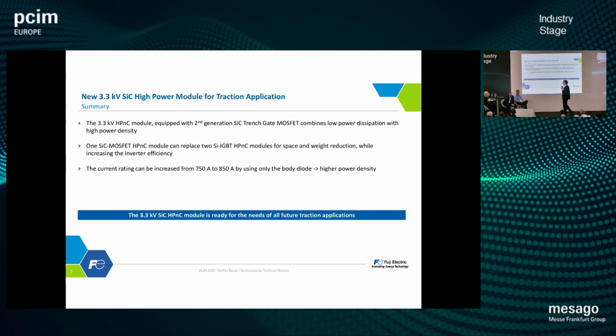So to summarize this, the 3.3 kV module is equipped with our second generation trench MOSFETs without Schottky barrier diode, and this combines very low loss dissipation with a high power density. With one module equipped with the silicon carbide chips, we are able to replace two modules in parallel with silicon IGBTs inside. And by leaving out the Schottky barrier diodes, we were able to increase the current rating in this package from 750 ampere to 850 ampere.